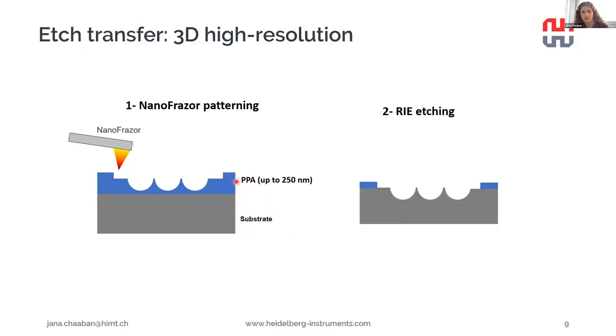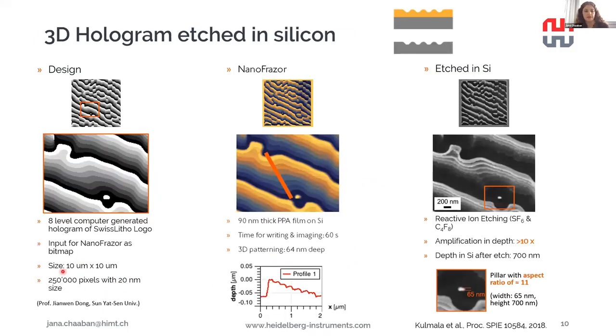So if we were to talk about a PPA and silicon substrate in this case, we have to keep in mind that the selectivity of PPA against silicon in etching is about 10 at maximum. So using this 250 nanometer layer of PPA, we would get a depth in silicon which is on the order of a few micrometers. If we want to amplify this etch depth even more, we can of course then simply add a hard mask layer underneath the PPA, and then we could virtually amplify this depth however much we want, depending on the hard mask layer introduced. So using this 3D etch transfer technique, we could create nice 3D holograms in silicon.